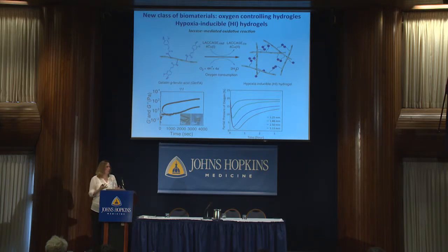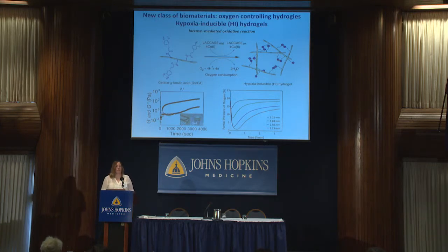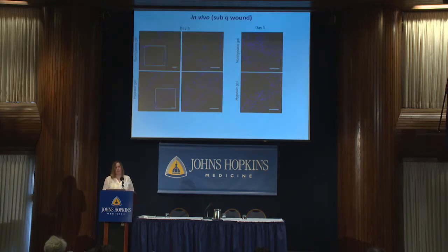So for that, we use that in our incubator. This is the first generation of this hydrogel. Now we can extend the period of hypoxia up to 10 hours just by the hydrogel. And we wanted to see what happens when we transplant those hydrogels as is under the skin. We could see that when hypoxic gels are transplanted, they induce much more new blood vessel growth into the hydrogels than the ones that are non-hypoxic.